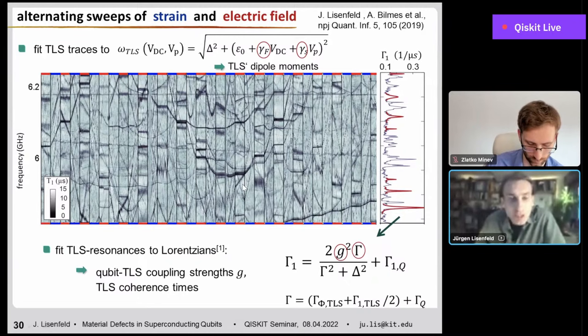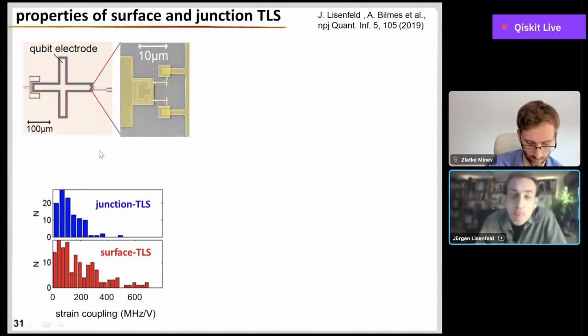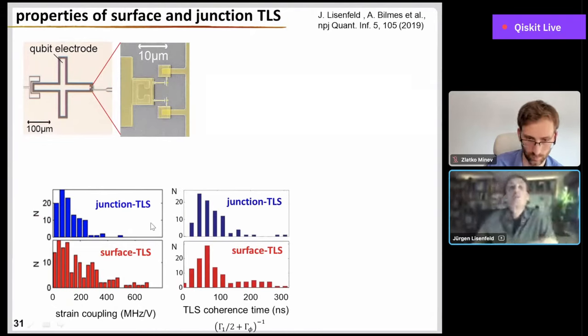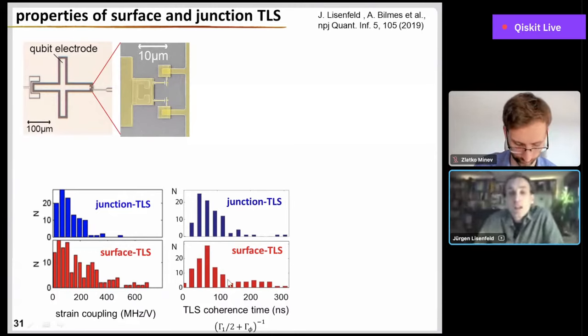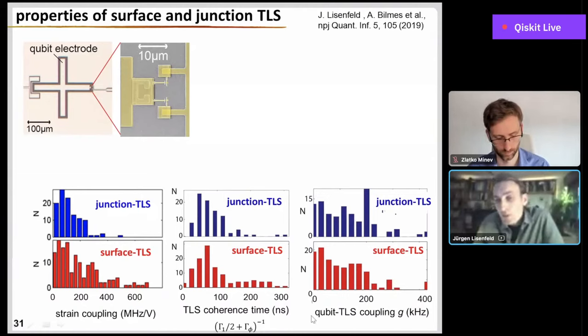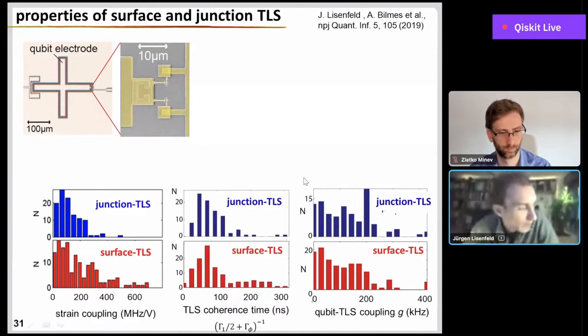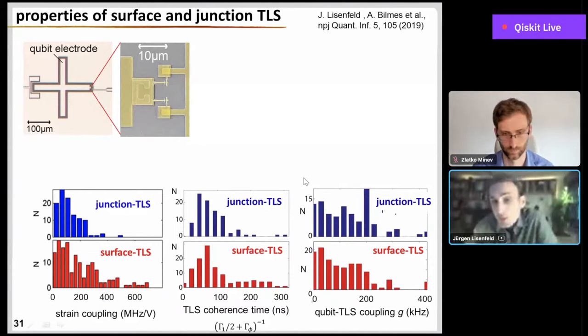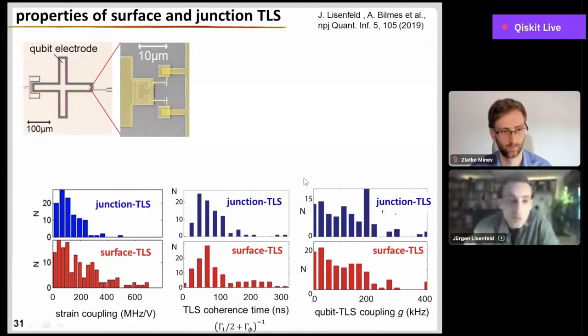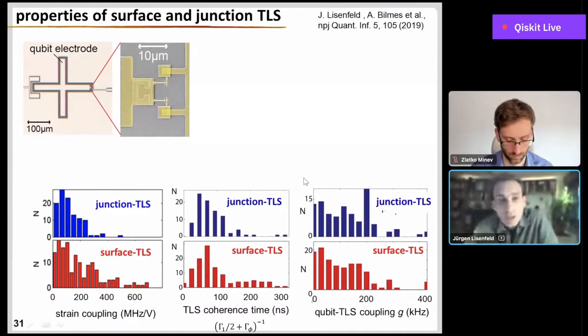And this is just some statistical analysis based on such data. So for example, we can, of course, separately plot values from the junction defects and the surface defects because we can identify them. And we find very similar properties for both of them. For example, they couple equally strongly to mechanical strain. Also coherence times are pretty much the same, and again, you see these are in nanoseconds here. And also their dipole moments are very similar for both types of defects. So in that sense, one could maybe say there's not really a need to postulate different models for defects there. These data seem to be compatible with a single defect type, which is also compatible with what we know from these glasses.